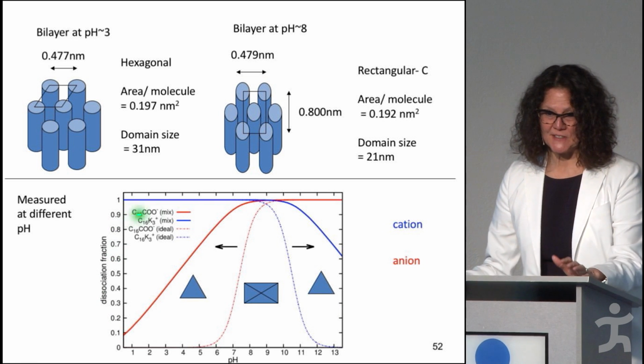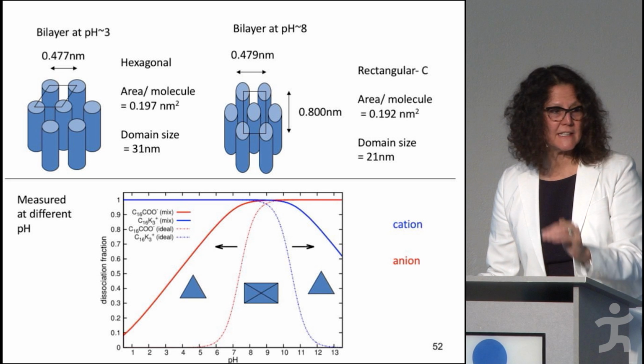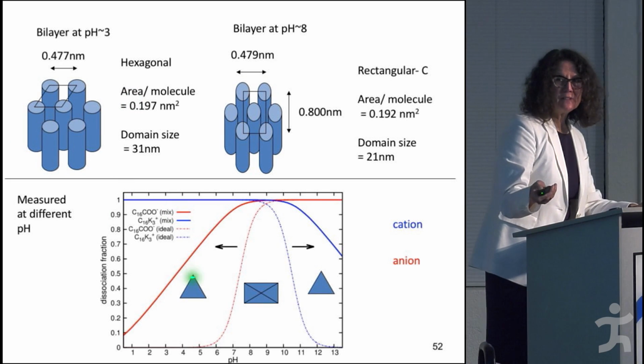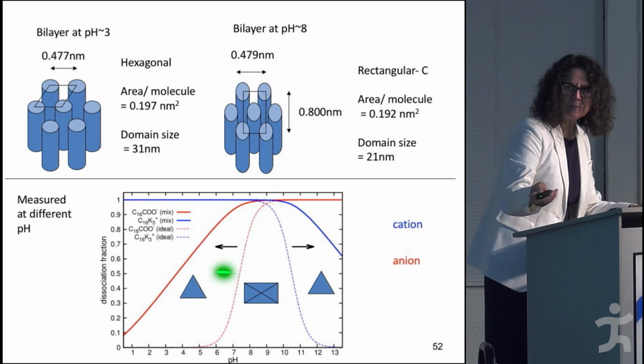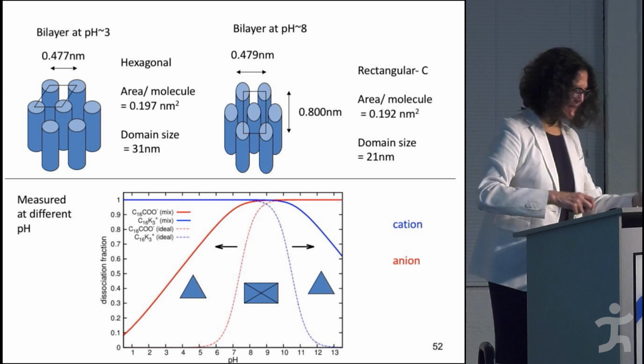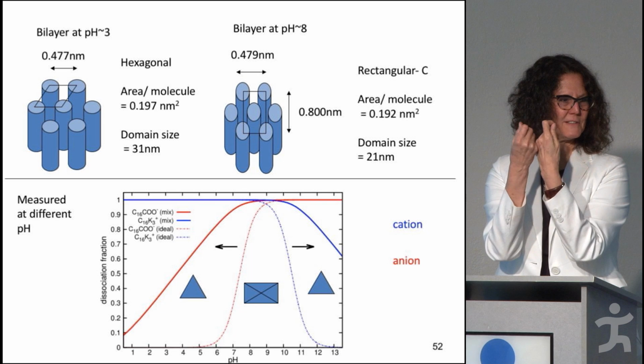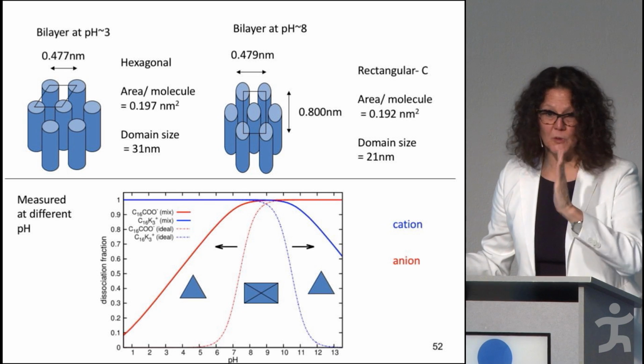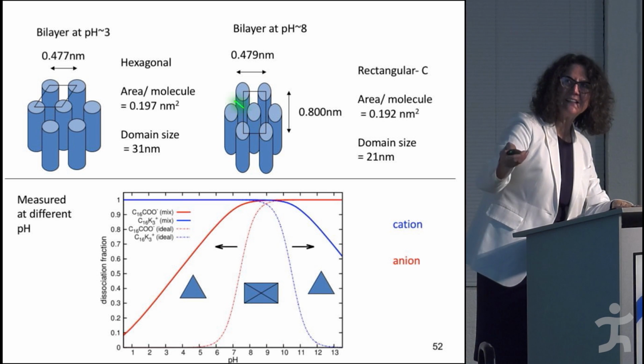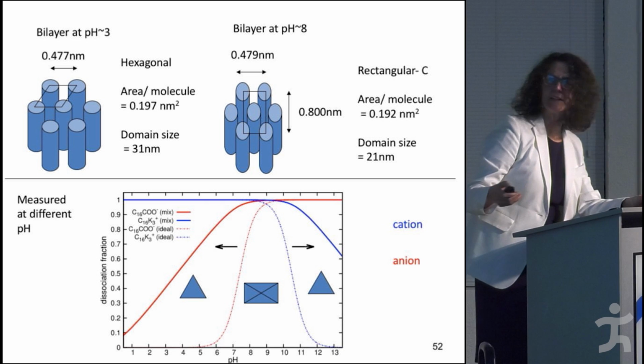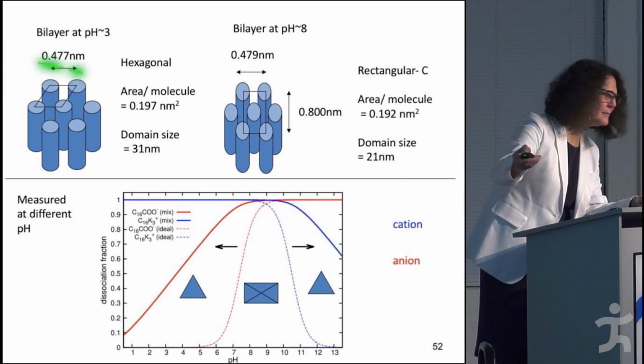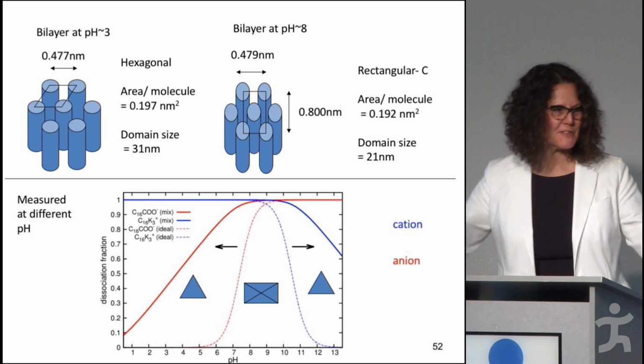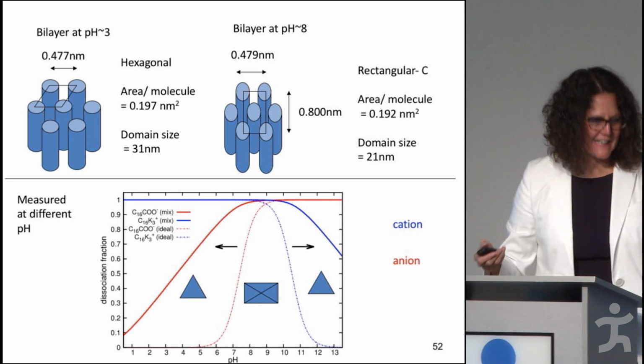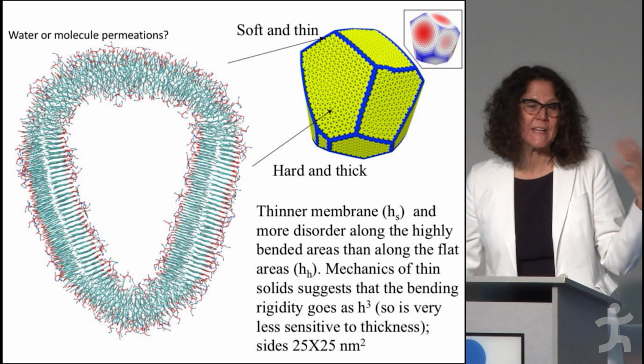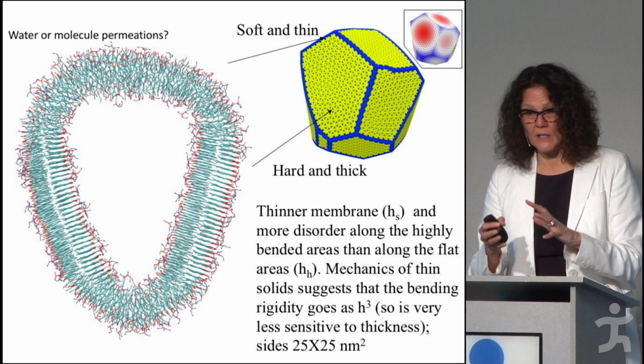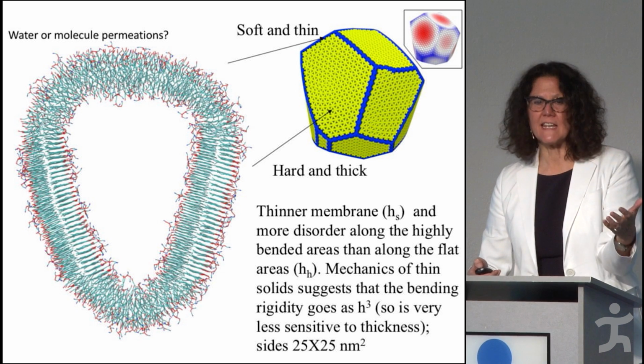What happened physically is that the tails were arranged in a different symmetry than the hexagonal. Okay? So if you have a pH 3 here in all these regions, and here pH large, small and large, the tails have the symmetry of hexagons, that they can rotate like that. This was done by X-ray. We could look at exactly how the tails are packed. And in this region, they are distorted. They are rectangular structures, called rectangular C. They are not hexagons anymore. So remember in the beginning, it was very important for all these theorems that you have these systems that come in any shape, but they are always hexagonally packed. So the conclusion we came to from this study is that when you have non-hexagonal packing in the layers, then they cannot close.